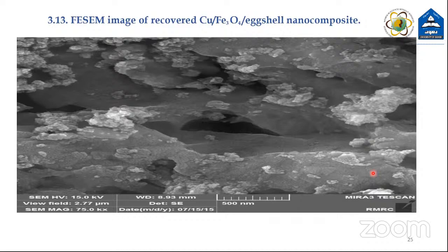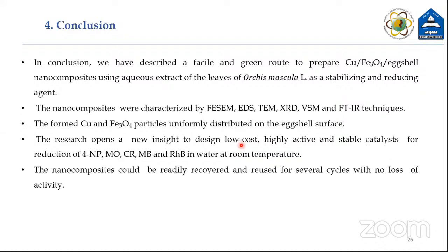FE field emission SEM images of the recovered nanocomposite revealed that the nanoparticles are identical in shape and size, even when used after 7 cycles. Conclusion. In conclusion,